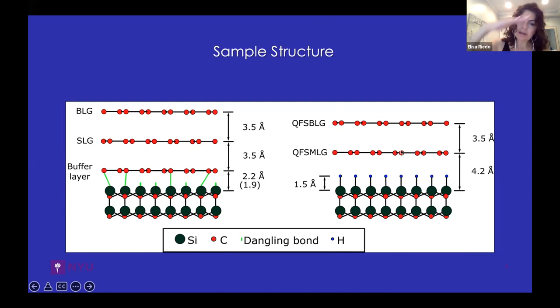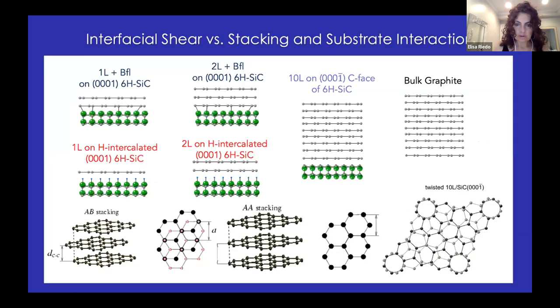So then again, you can have one quasi-freestanding, two quasi-freestanding monolayers, and so on. And you have hydrogen here that saturates the dangling bonds of the silicon carbide. So these are all the systems that we have studied. We have one layer graphene plus buffer layer on silicon carbide, two layers plus buffer layer, quasi-freestanding one layer with the hydrogen intercalation, and then two layers with the hydrogen intercalation.